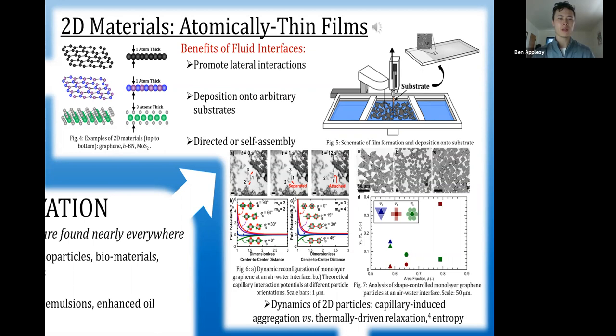In the green curves, if the particles are able to align themselves in the ideal orientation, they experience a weak but continuous attraction towards one another. But if they become misaligned, they begin to experience repulsion at very close distances, seen by the purple and red curves in figures 6b and 6c. By examining the interaction potential, we determined that the magnitude of attraction interactions were weak and could be balanced by thermal energy or Brownian motion. In figure 7, some recent progress is shown in creating size and shape controlled graphene particles and we are beginning to understand how shape influences the order of the system.